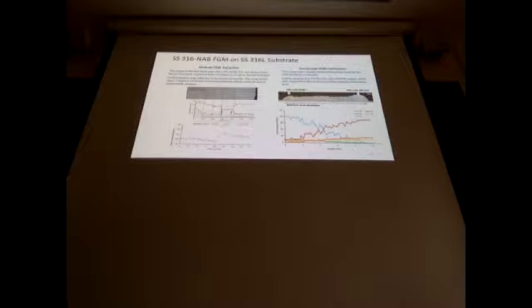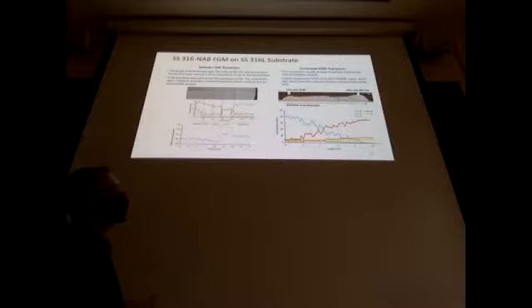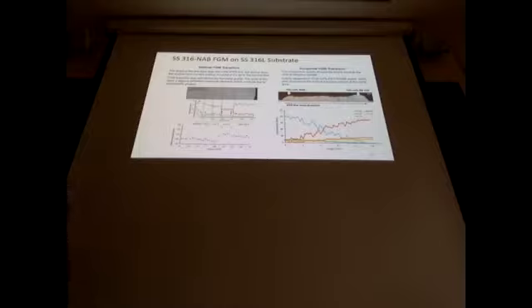You can see some issues here that we found, like some cracking right at the stainless steel, which makes sense because stainless steel can be problematic when you try to add, especially nickel, into the system. So it actually becomes prone to cracking. And again, right now we're in the phase of doing characterization. My student is trying to understand the characterization and bring that back to the model, modify the model, and hopefully we can have a control structure that we're hoping to use for our future functionally graded materials as well. So that kind of finishes that up.